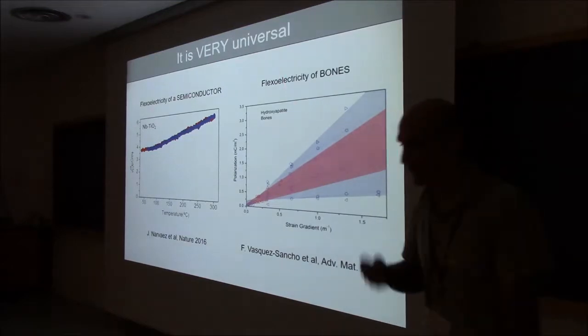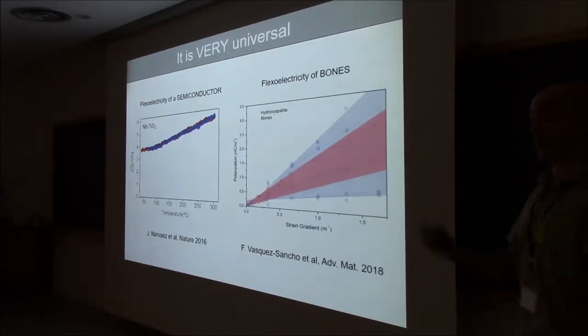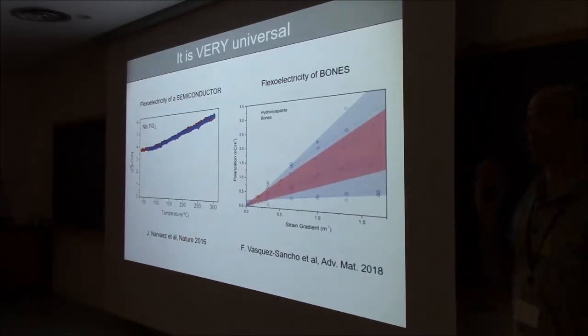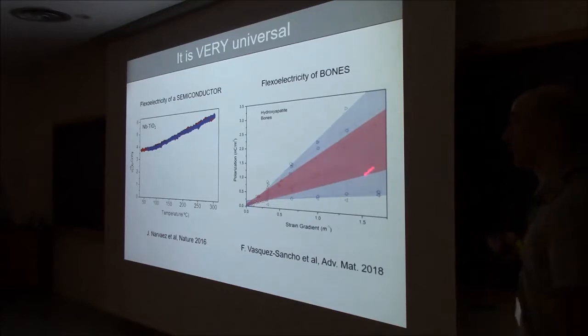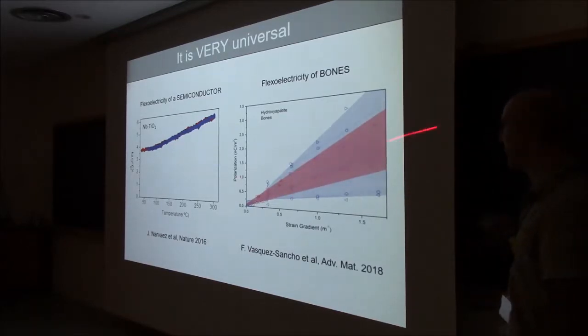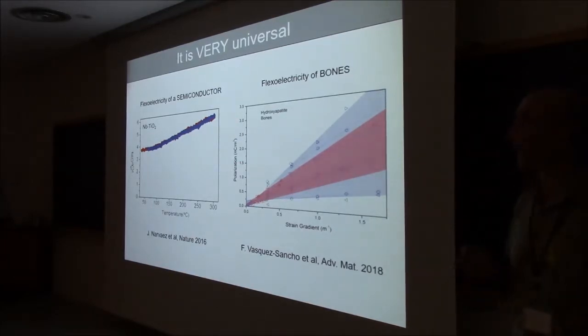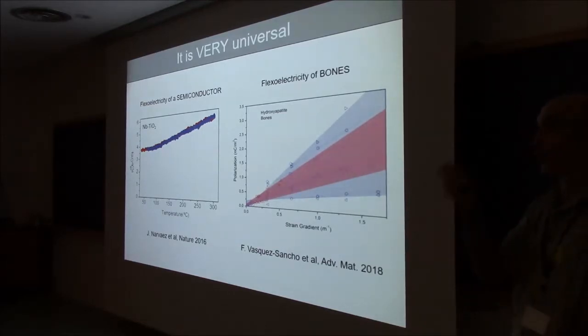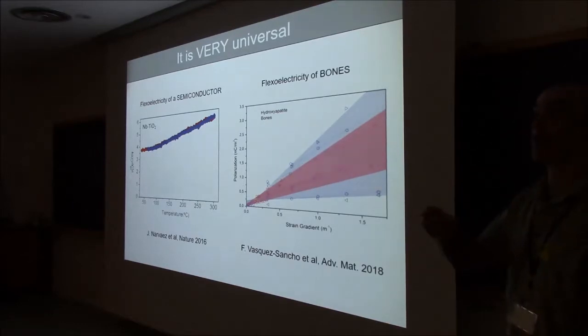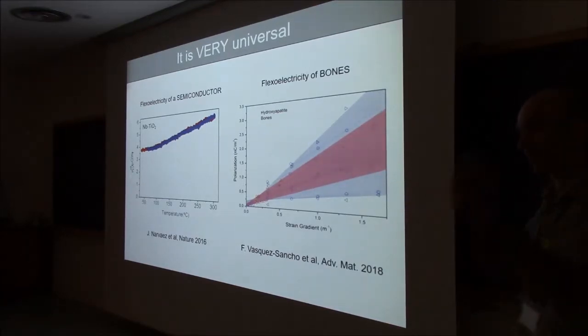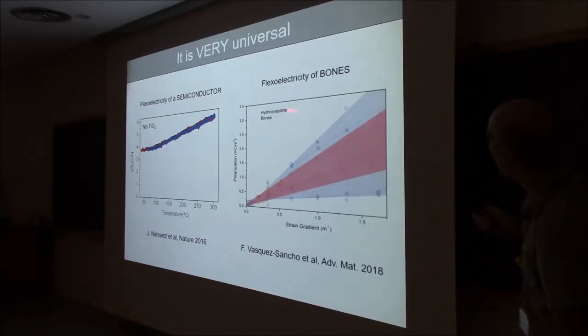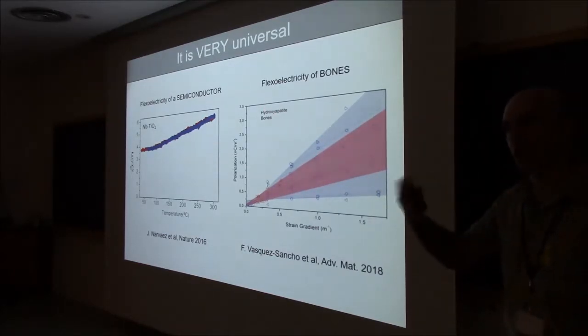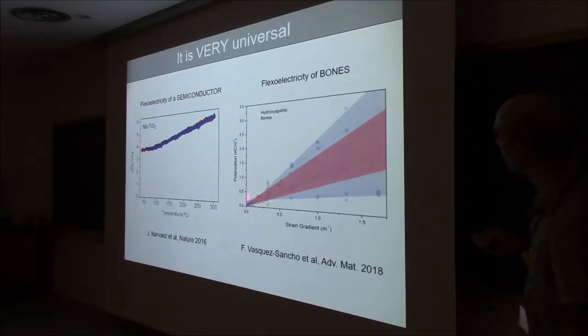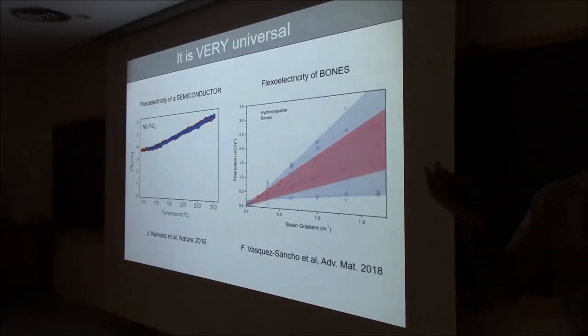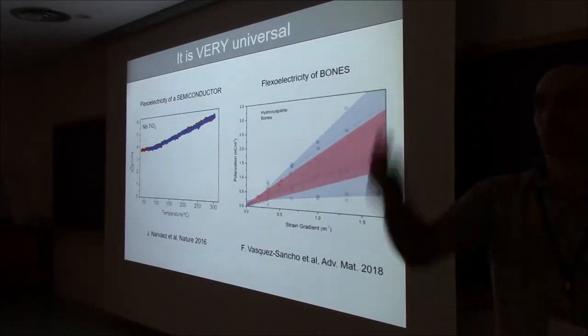And it's very universal in the sense that it exists in all ceramics, in all dielectrics, in all semiconductors. It also exists in biomaterials, including your very own bones. Well, I haven't measured human bones, but I assume that they are not going to be very different from pig bones, which is what we measured here. And as a function of strain gradient, you get a polarization. And that polarization is due to flexoelectricity, not to piezoelectricity. So bones do have collagen, which is piezoelectric, but if you get rid of all the collagen, you make the pure bone china ceramic, so pure hydroxyapatite, which is centrosymmetric, not piezoelectric, you still get the same bending-induced polarization. So flexoelectricity exists inside you, which is kind of cool, right?